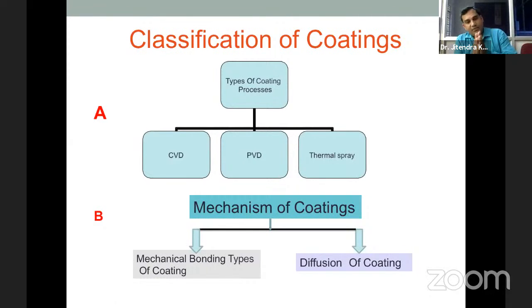So because of this mechanical bonding, whatever the coating falls over the surface, the best thing is if you can functionalize the surface by using the oxygen plasma cleaner. Only then is this mechanical bonding better, because by oxygen plasma cleaner you can generate the OH group over the surface, and then if you coat that, it's mechanically bonded strongly. Otherwise it can detach after some time.